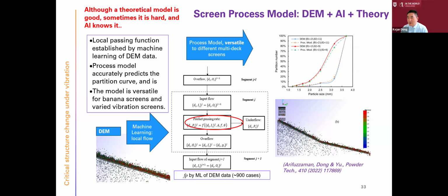So although that is a very specific case, we also tried to use our understanding of the effect of vibration on the particle structure change. Even in the vibrated bed, we have the percolation, we have the segregation. We find that vibration velocity amplitude is a better parameter to characterize those dynamic behaviors. That's what we learned from when we did the self-assembly. But as I noted here, a theoretical model is always good, but sometimes it is very difficult to obtain,